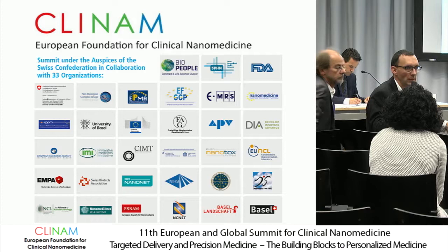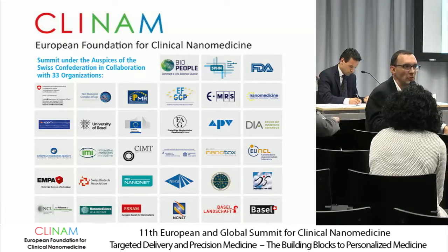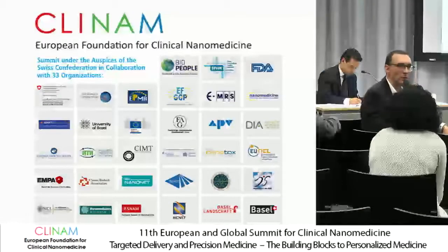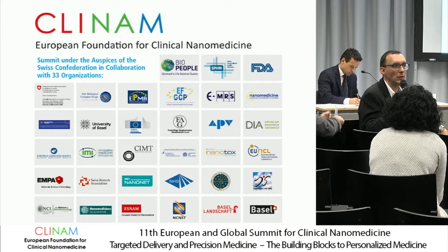In terms of extracellular vesicles or biologicals, we know a little bit about refractive index, so it's not super high, such as for gold or inorganic materials. So we have some estimates, and if you take the average, you're quite close. It's also a question: are we talking about 1%, 2%, 5, 10, or 20% error, which is acceptable? The higher your constraints are, the more you have to treat your data or take care about the measurement of the samples. For extracellular vesicles,